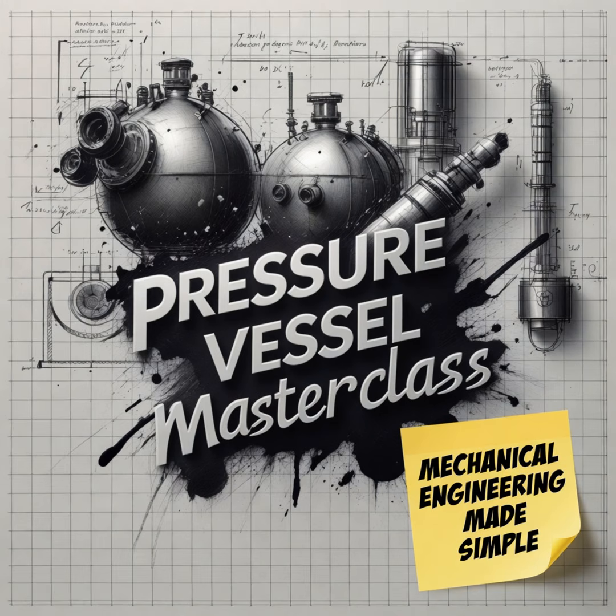A huge pain point. Right, because if cold temperatures turn steel into a twig, the codes mandate strict Charpy V-notch impact testing to prove the steel can actually take a hit at the minimum design metal temperature, or MDMT. Yes, they do. But the texts point out that impact testing every single heat of steel is massively expensive and completely wrecks procurement schedules. So how do engineers avoid the massive expense of impact testing for low temperatures? It is a massive bottleneck for projects. But the code does provide 3 primary, perfectly legal engineering workarounds to avoid the expense of impact testing.